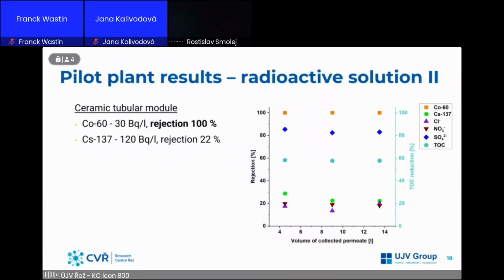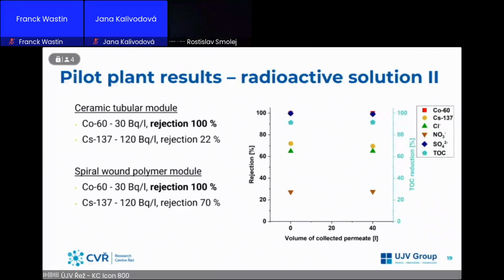And we also finished, so far, experiments with the second radioactive solution, where both of the membranes had complete rejection of the cobalt, which was very good news for us. The cesium rejection for the ceramic module stayed similar to the previous experiments, while the polymer module was also as good as the previous one, between 70 to 80%, when we expected 10%. We were very, very pleased about these results. We also started to look again into the rejection of other ions, just to see the overall behavior and what the resulting pyramid looks like.